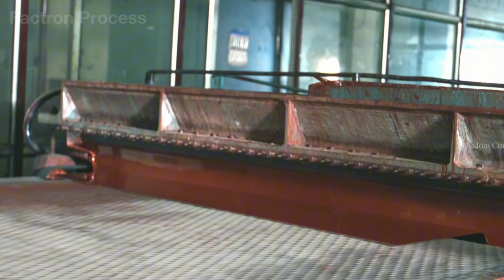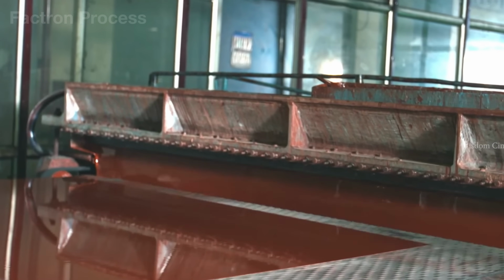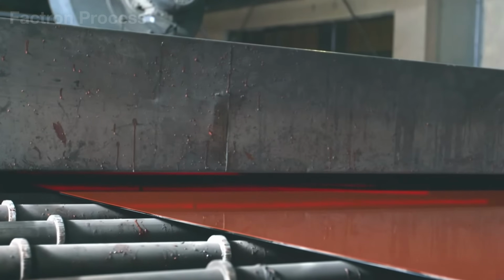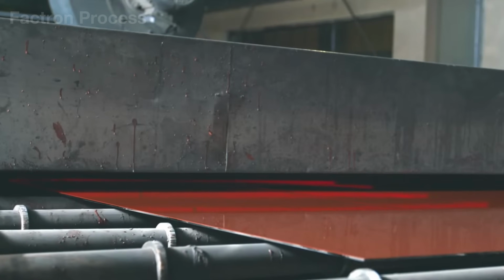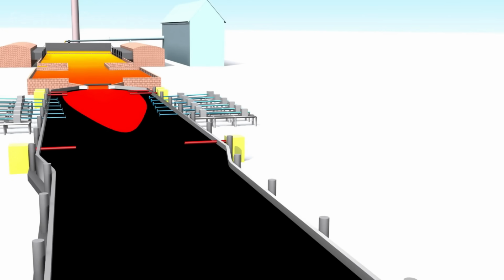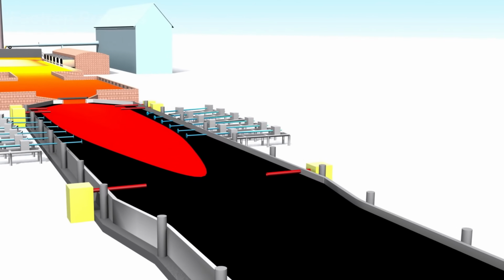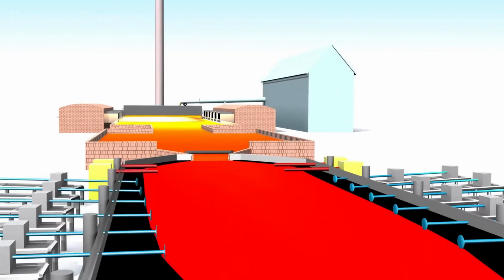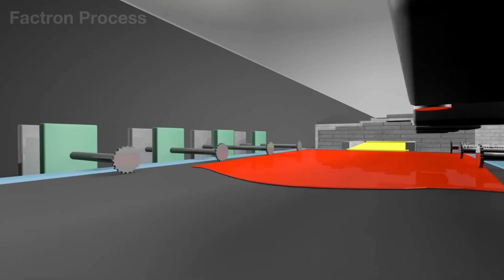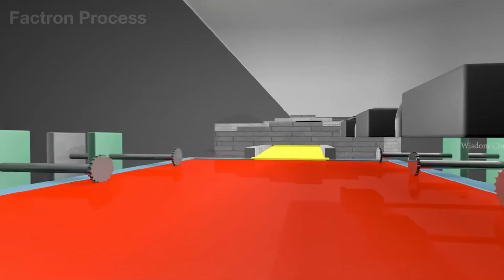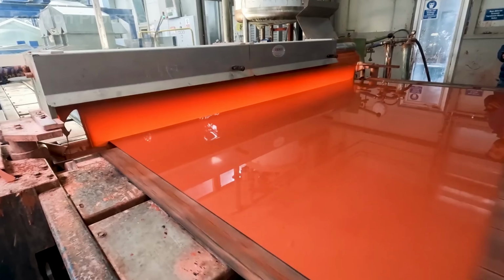For flat glass, the greatest breakthrough in the industry was not melting the glass, but finding a way to create a perfectly flat surface. Float glass technology, introduced in 1959 and now used for nearly 90% of the world's flat glass production, completely transformed how glass is made. Instead of being pressed or rolled like many other materials, molten glass is guided from the furnace onto a bath of molten tin, hundreds of feet long.